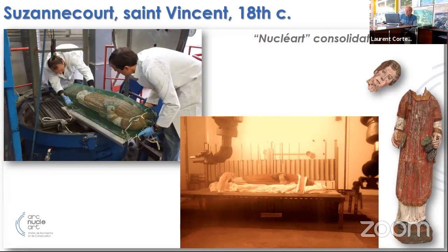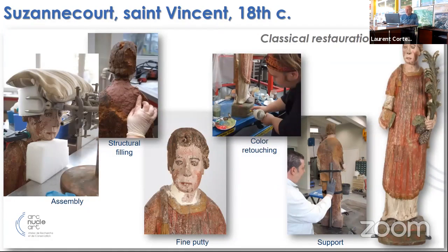Then the different pieces were impregnated with the styrene polyester resin, and after it was irradiated to make the resin harden. And at this stage, it was possible to reassemble and to do again classical restoration with some structural filling, fine putty, color retouching, support, before it could be exhibited again. I think this is really a good illustration of what is the last chance. And you can see also it does enhance a bit the color, which is not what we were looking for, but in this case, it's okay.